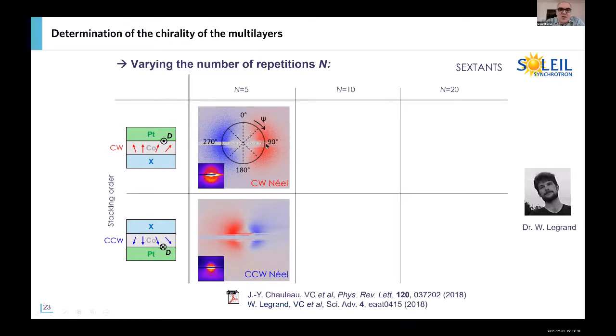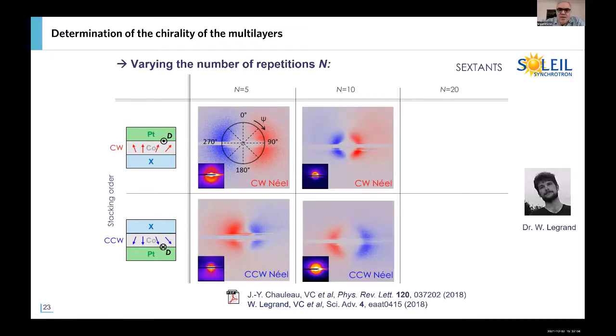And second, we see the order of the colors, like here the blue, white, red, the French flag, means that we have a clockwise chirality, as expected when we put the heavy metal onto the ferromagnets. Now, if we prepare the same sample but with opposite stacking order, you see that we get exactly the opposite contrast. So as expected, we can characterize Néel domain walls and their chirality.